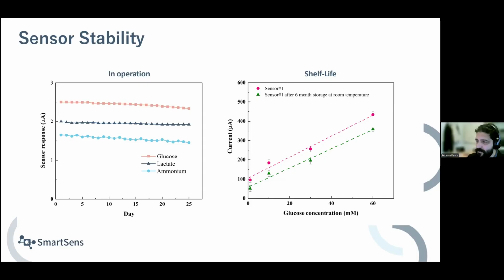About the stability of the sensor, this is the very big advantage of having bio-free sensors. In operation, we tested it. They can last for 25 days. Of course, the response drops. You can try it more if you want to. And the shelf life stability, we tested it after 6 months. So basically, you can leave the sensor at room temperature in the lab environment, and then you come back and use it again. This is very important, for example, for single-use bioreactors where you may need a long shelf life stability.